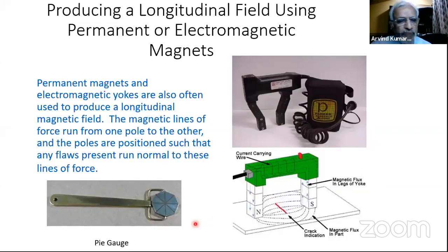to see that all kinds of oriented defects you are able to pick up. And this is what is called a pie gauge, which is used to indicate the direction and the strength of the field. Once you have magnetized, you can introduce this into the magnetic field, with these lines, which we just tend to call crack-like things. It should be upside down, and from the upper surface, after it is magnetized, you put dry powder or wet powder. Generally, it is dry powder, and you will see that these lines are appearing on the other side of the pie gauge. That means the field strength is adequate, and it is picking up these indications. So it may pick up the defect indication also.